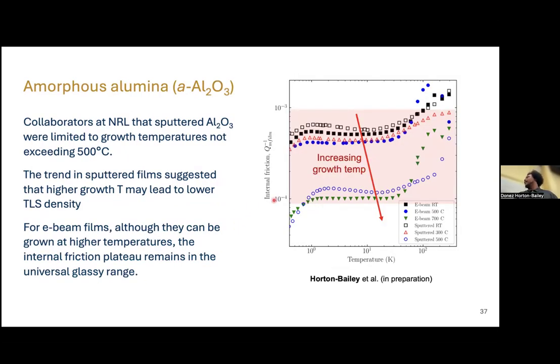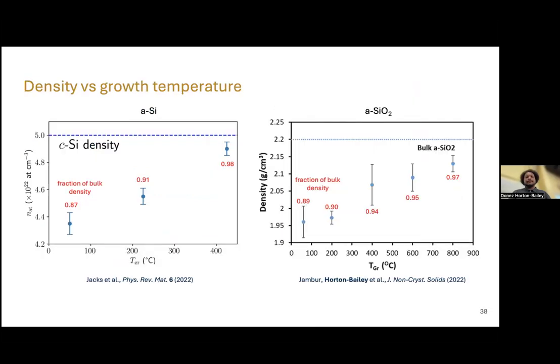Amorphous alumina, this is another case where, in addition to increasing the substrate temperature, we also did some post-growth annealing, meaning we just put it into a furnace, set it to a high temperature, and let the atoms that are already in the film wiggle around and find their new positions. This caused the internal friction to go down slightly in each case, but nothing significant below the universal range. Again, this universal range ends around here where this green line is. We would expect to see things several orders of magnitude below for it to be useful.